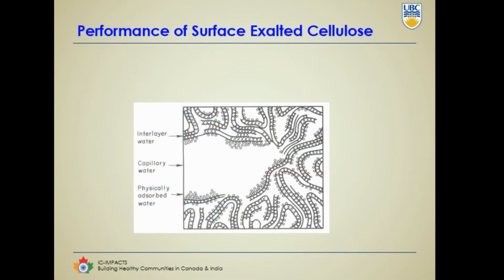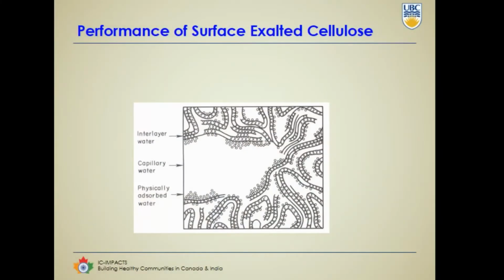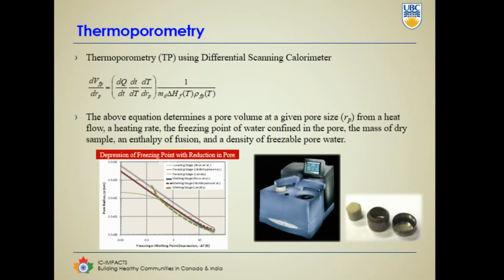So let's take a look at what we have done with the fibrillated cellulose in concrete itself. I'm going to show you a couple of tests. One is thermoporometry, and I'm sure some of you have already used it before, where you're freezing the system. When you freeze the system, if there is pore refinement, you would get more supercooling because the water in those pores is under absorption. So it shows more supercooling in the system itself.